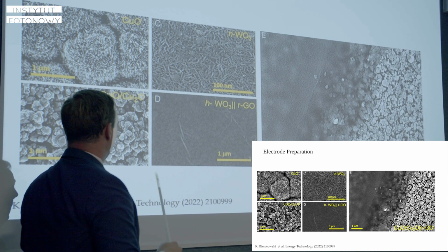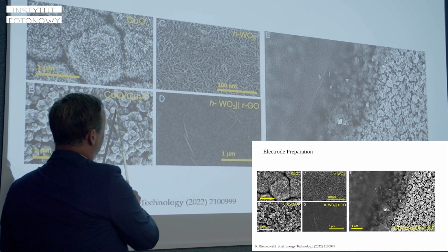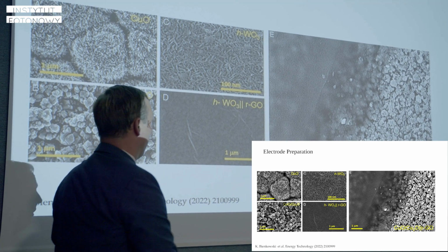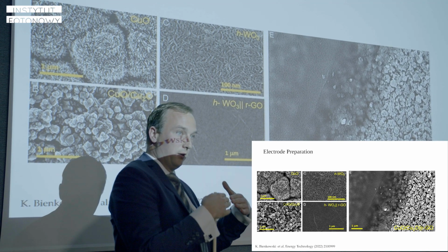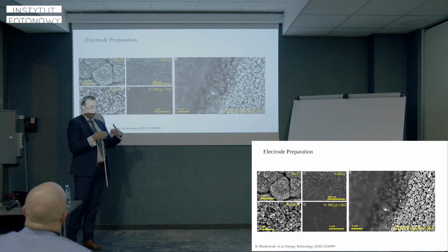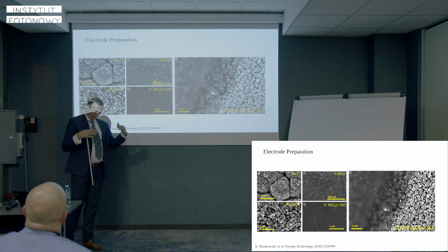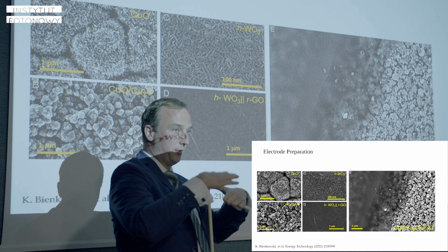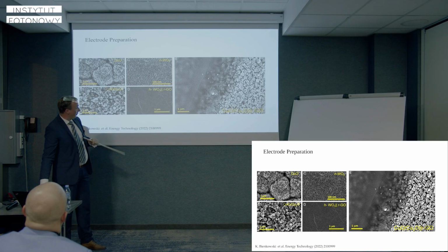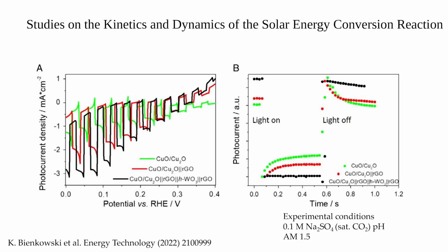Because we know the Fermi level position of this system and the work function of hexagonal tungsten trioxide, we can use specific layers of reduced graphene oxide to have the best position of the Fermi level of all these materials. And so finally, I would like to show you